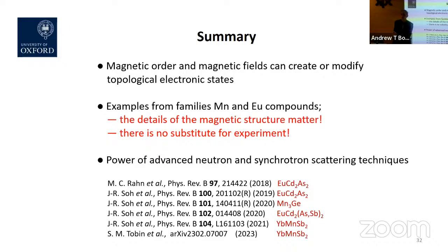I'm not sure whether this is his question, but one of the tricks for solving magnetic structures is to look at the possible symmetry-allowed magnetic structures, assuming that when the system goes from the paramagnetic phase to the ordered phase, it's a continuous phase transition, and therefore one can conclude that the magnetic structure should be a single irreducible representation of the paramagnetic space group. If you make that assumption, then you get a small number, usually 3 or 4, of possible structures to look at.